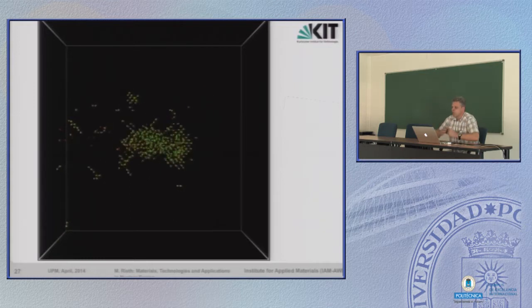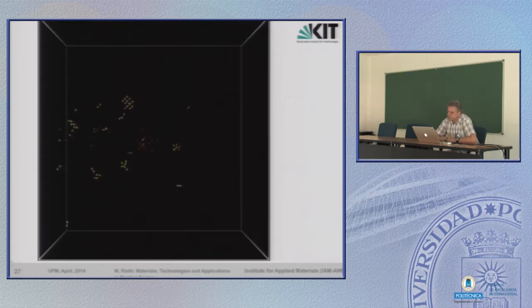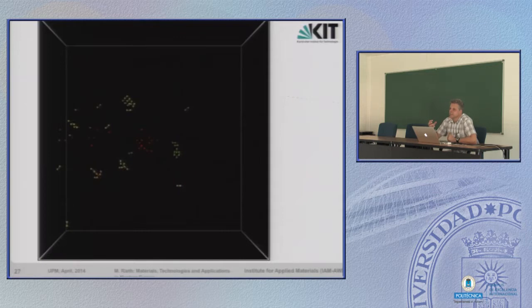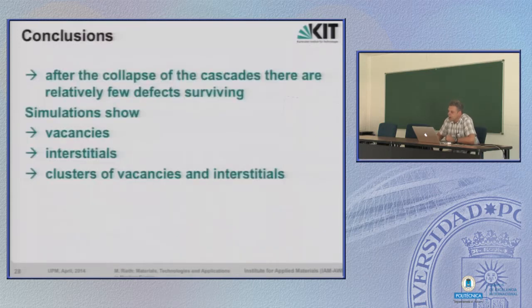Also here, another example, cascade. First, it's blooming up, producing a lot of Frenkel pairs, but in the end, there is only a small number of defects surviving. And what you can see, the red points and the green groups of points, these are clusters, defect clusters, which is the leftover of a cascade. In the end, there are only a small number of defects, Frenkel pairs or clusters of vacancies and interstitial atoms you can see. However, that's causing enough trouble.